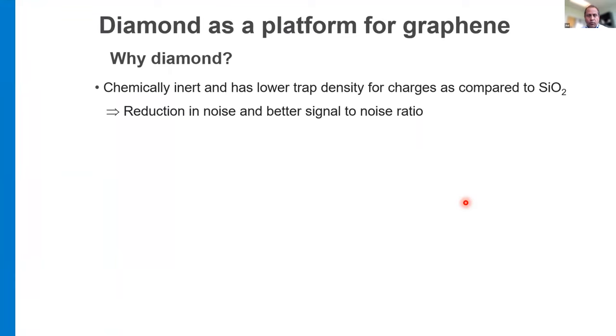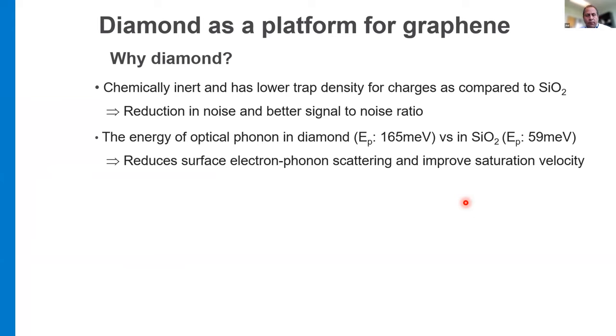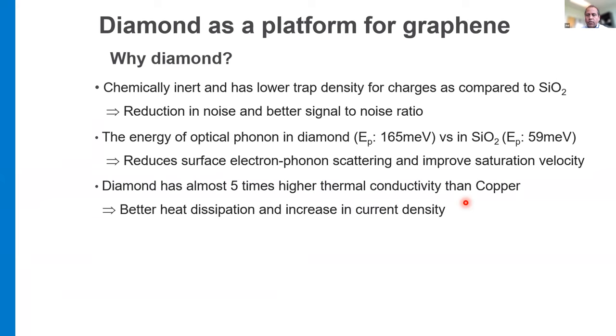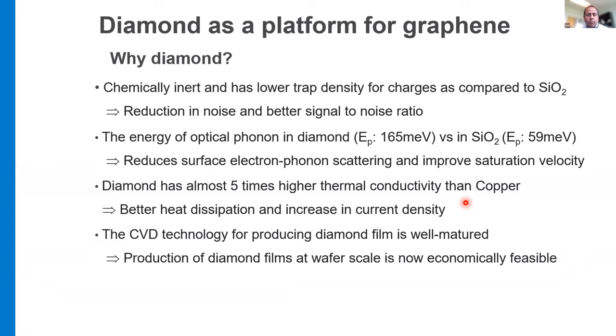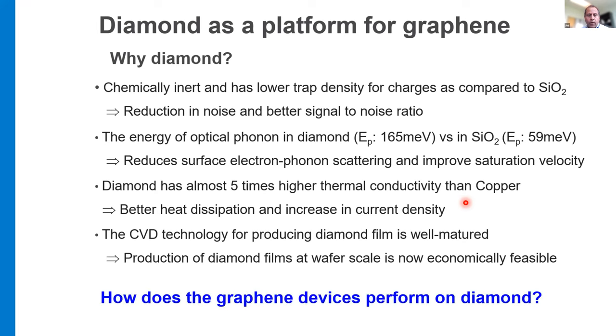So the question is, of course, why diamond? Because it's chemically inert, and has a very low trap density of charges as compared to SiO2. So that helps in the reduction in noise and getting better signal to noise ratio. Also, diamond has a very high energy for optical phonons as compared to SiO2. So that reduces the surface electron phonon scattering to improve the saturation velocity. And of course, diamond has a higher thermal conductivity than SiO2 and then copper. So it's a better heat dissipation to increase the current density. And with the CVD diamond technology I already mentioned, which is well matured, you can have diamond wafers at different wafer sizes and even including now single crystal diamond.